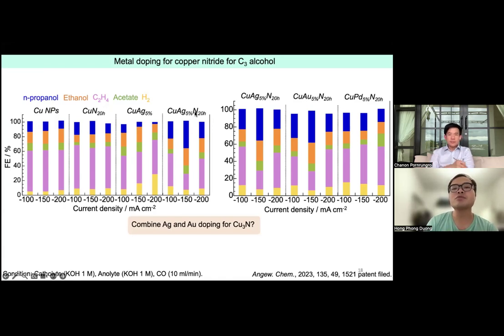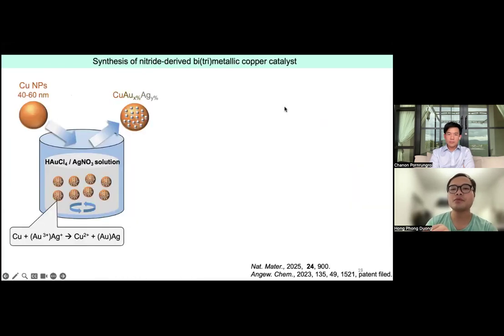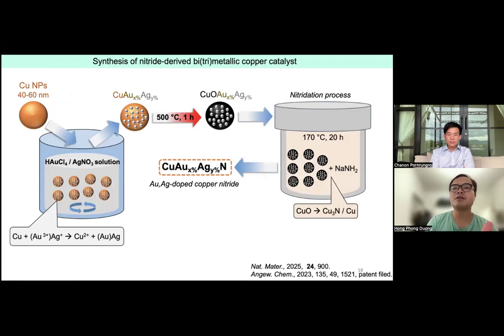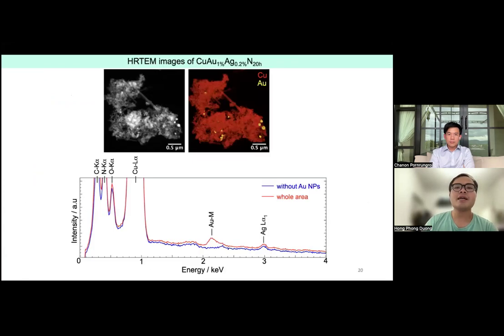So this result inspired us to try more with other metal doping. We also tried gold and also palladium. We found that silver and gold were very good to make n-propanol. This was in fact our first result; I remember it was in the second year of my PhD. So we found they are very good, and this is why we make gold and silver together with copper, not just only one metal. And the characterizations of the trimetallic compound with nitrogen were very, I would say, very intense.